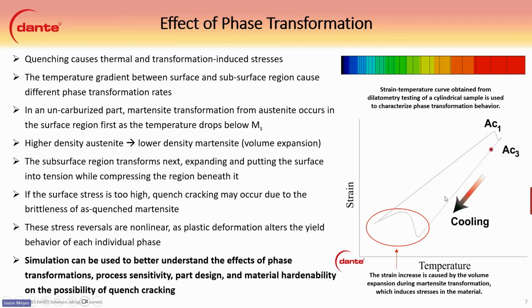So over to the right here, we have a little animation that's running that basically shows the heat treatment process and the phases for the steel. Upon heating, it goes up to the austenite start temperature. It drops in volume, increases in density, when it converts to austenite. And then as it's cooled, it converts to martensite, and you can see the volume expansion here on the dilatometry curve here. That large volume change here is what we were talking about with pulling the surface into tension.